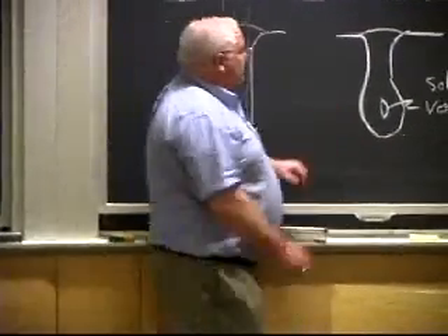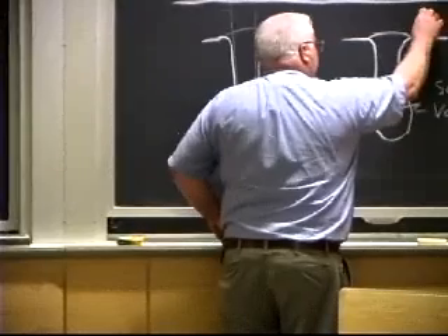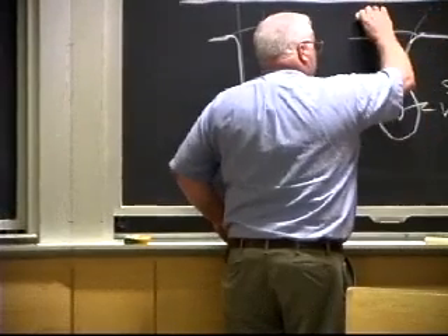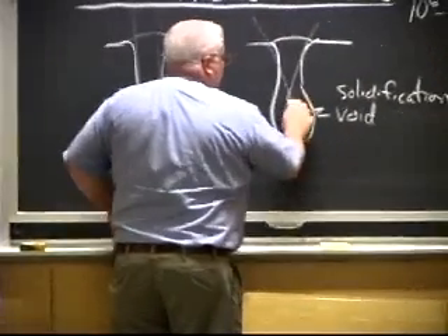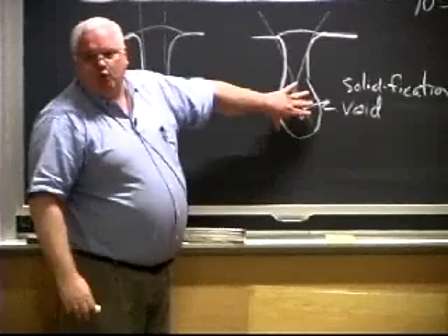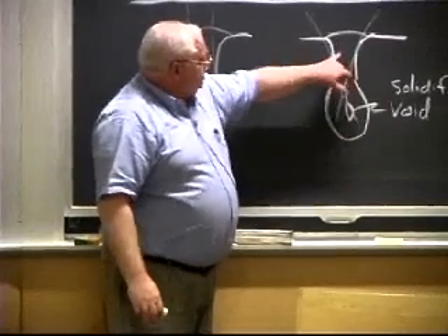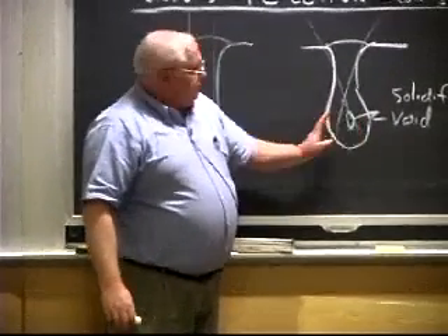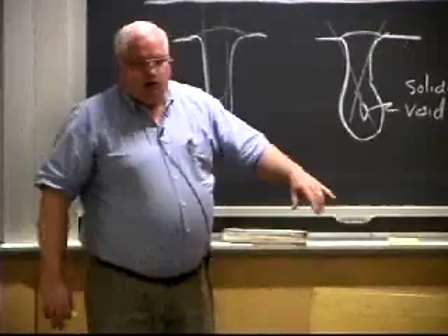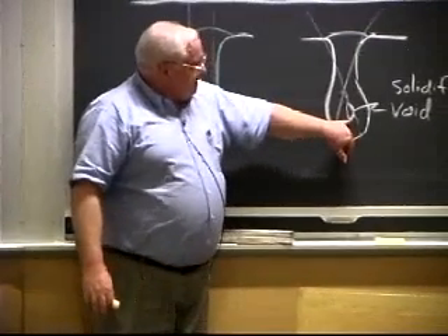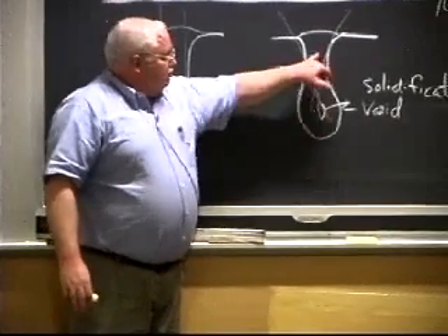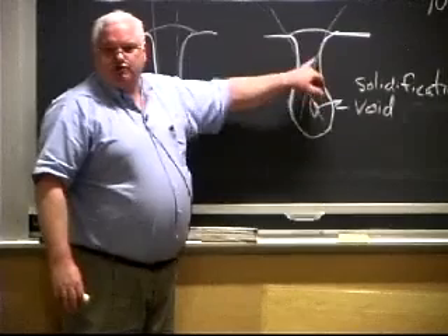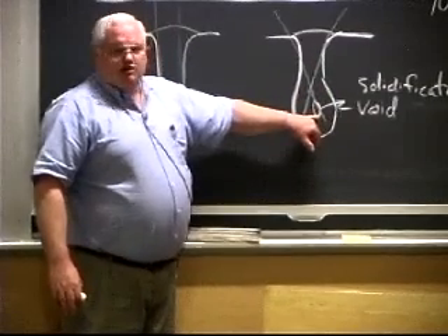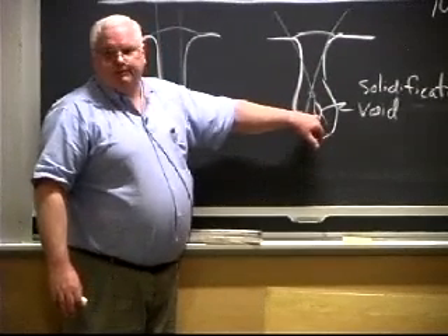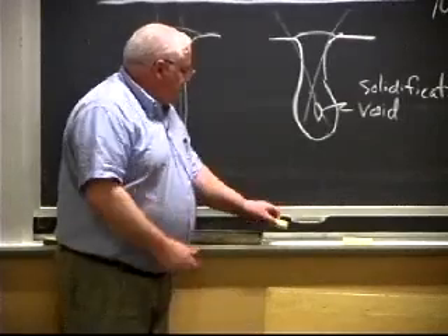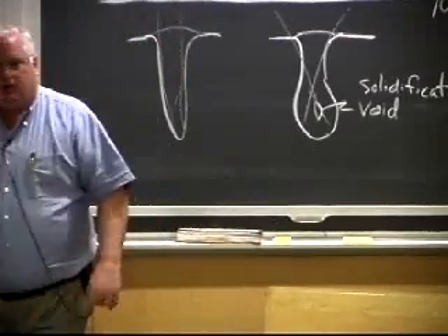The reason for that is if you have a poor focal length, a short focal length, which I haven't drawn very well, you'll generate most of your heat down at one area. You'll have a sharper focus there than up here, and that means you'll end up with a weld pool that's pear-shaped or something. If you do that, you're going to find that you don't have a good casting geometry. As the metal solidifies and shrinks, you're going to end up with voids here. And somewhere in my files, I've got a picture of that very thing. Okay.